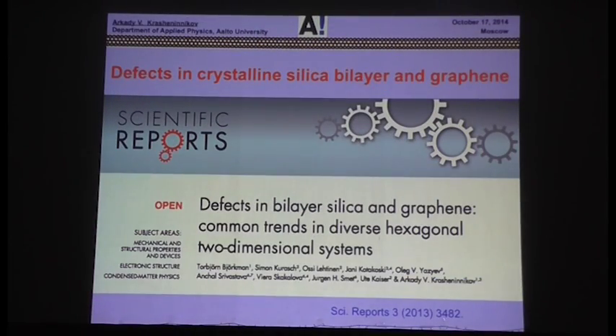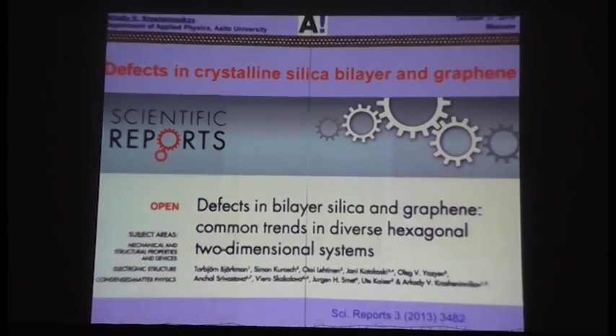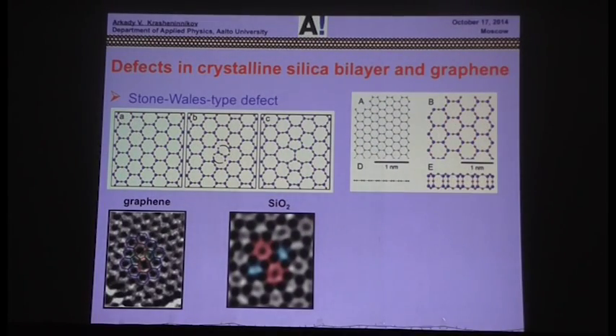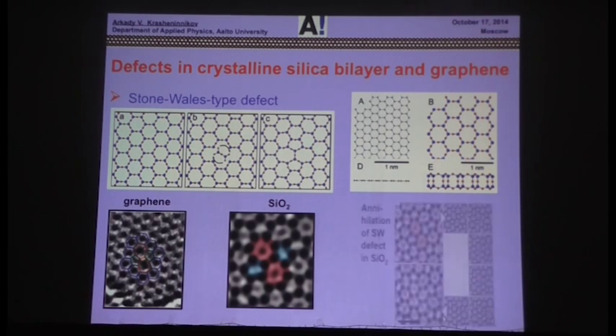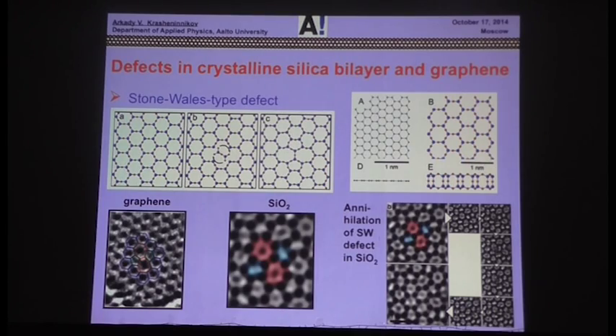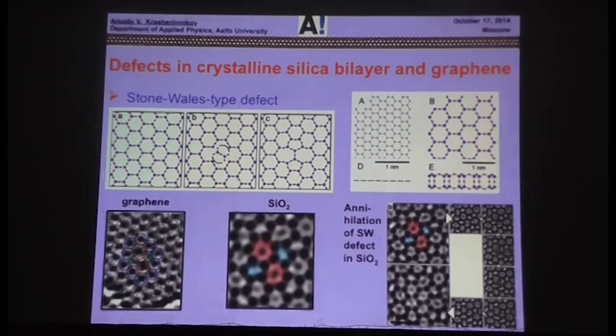Okay, and recently we looked at defects in these materials, graphene and SiO2, and what's interesting is that the motifs of defects in these two diverse systems, recall that graphene is a semi-metal and silica is a wide-gap insulator, but the symmetry is the same, relative view, top view. So this is an example of a Stone-Wales defect in graphene and a Stone-Wales defect in SiO2. Also, in real time, microscopists can see transformations either way.